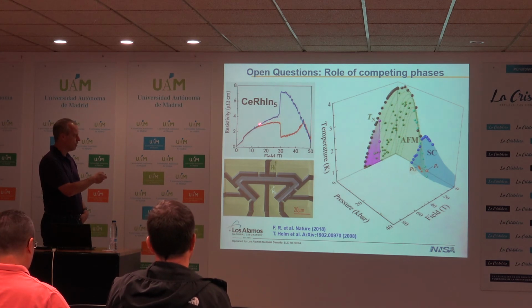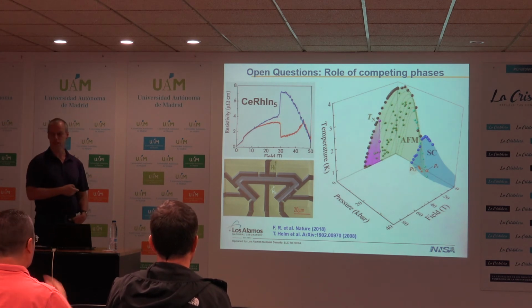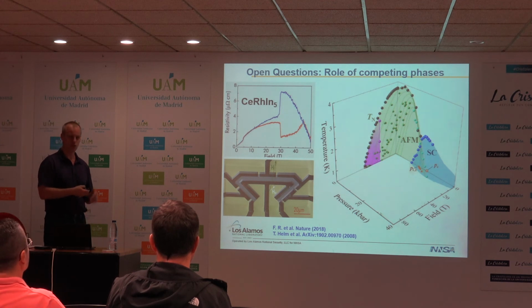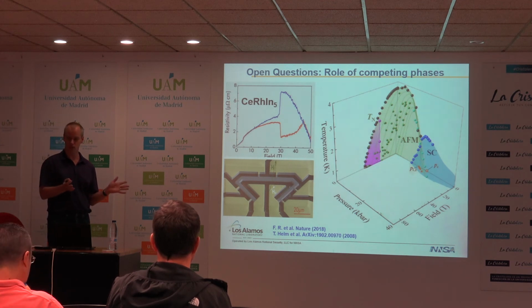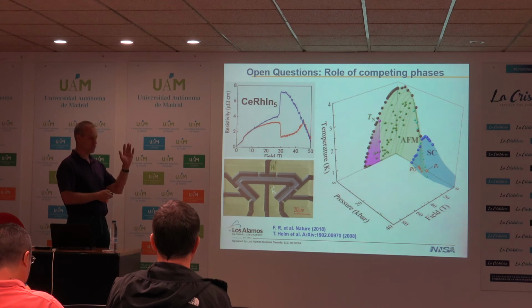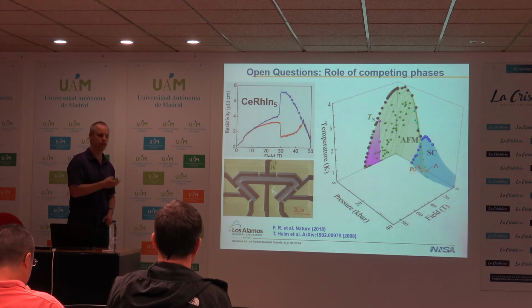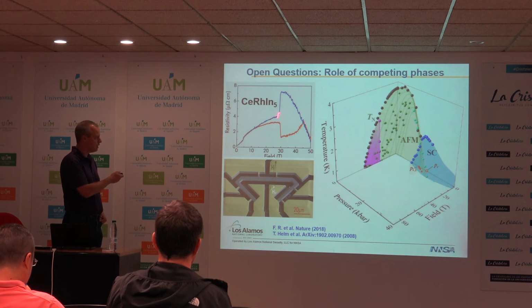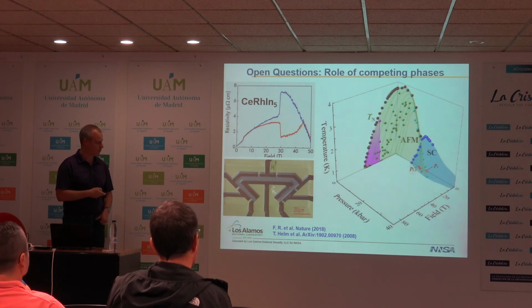Now this is rho A and rho B in a tetragonal compound, so nominally they should be identical. The magnetic field is tilted a little bit away from the C-axis, so you expect one leg to have a little bit more transverse magnetoresistance than the other leg, so small splitting. But at 30 Tesla there is a clear first order phase transition where you have a jump in the resistivity. It changes by essentially a factor of 2 in the two legs.